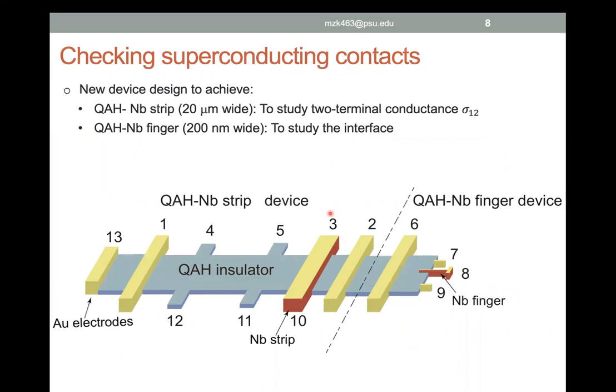So I made these samples. This is done with lithography. So I used the e-beam lithography here. So this sample actually serves a bunch of different purposes. So first, I have a normal Hall bar, which allows me to check the quality of the sample. I have a superconducting strip. The width of this strip is 20 micrometer. And this would allow me to measure the 2 terminal conductance.